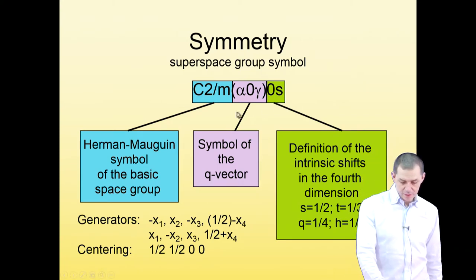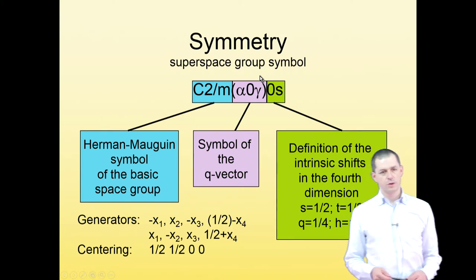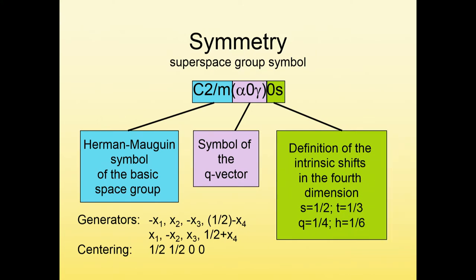The second part contains the definition of the modulation vector. So it gives a general description of the modulation vector, and this case is a modulation vector which has non-zero components along A star and along C star. So it's alpha, zero, gamma, saying that the second component of the modulation vector is zero. So the modulation vector lies in reciprocal space in the plane A star, C star, with no component along B or B star.